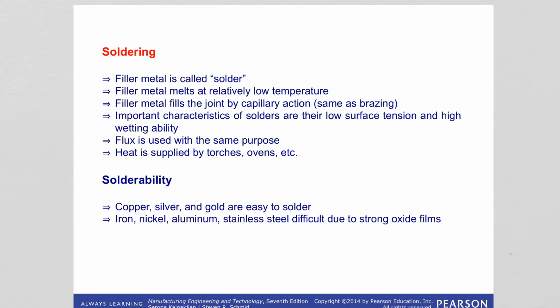Advantages of this technique are low energy input compared to brazing and fusion welding, a variety of heating methods available such as torches and ovens, good electrical and thermal conductivity in the joint, and it is easy to repair or rework. Disadvantages, on the other hand, are low joint strength and possible weakening or melting of the joint in elevated temperature service. Two important characteristics of solders: their low surface tension and high wetting capability.